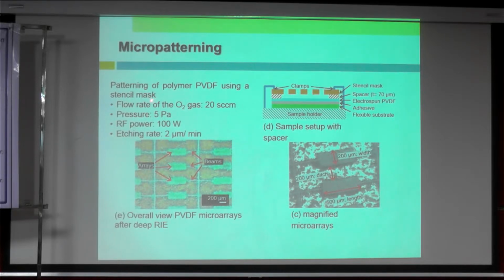Then patterning with the deep RIE with a gas flow rate of oxygen and pressure, RF power, etc. You do the etching of this PVDF membrane. Then these are quite important parameters for a certain process, because, depending on the material that you are dealing with, the process might have a different recipe. So this is the actual photo, zoomed, with a 200 micrometer width of PVDF. So you just imagine, yesterday we talked about our hair at about 50 to 70 micrometer. So this is just slightly bigger, 200 micrometer.